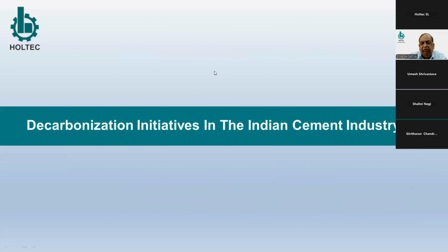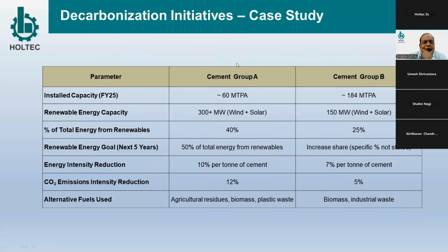So if we talk of decarbonization initiatives in the Indian cement industry, we will take two groups in this. Just installed capacity 60 million, 184. Renewable energy 300 plus megawatt, wind plus solar, another 150 megawatt. Then 40% total energy from renewable, and then 25%. So we can see renewable energy has gone up. Their target is 50%, and in the other case, it will be significantly increased. Energy intensity reduction is 10% and 7% in the other case. CO2 emission intensity is 12% and 5%. So this is the current situation with the two groups, and it looks that most of the plants are now pushing for decarbonization with significant speed.